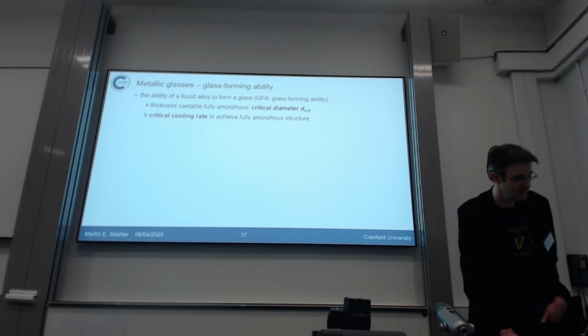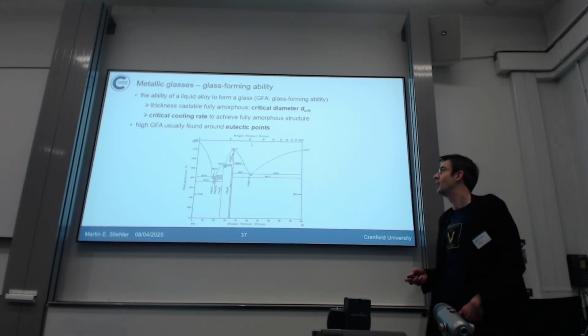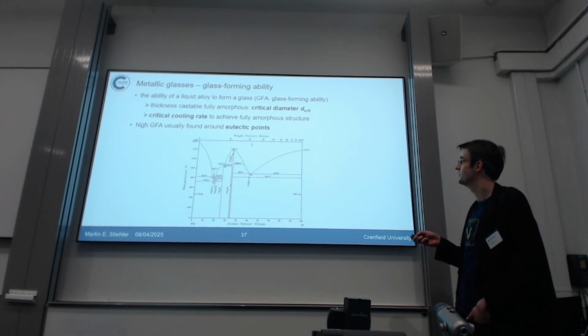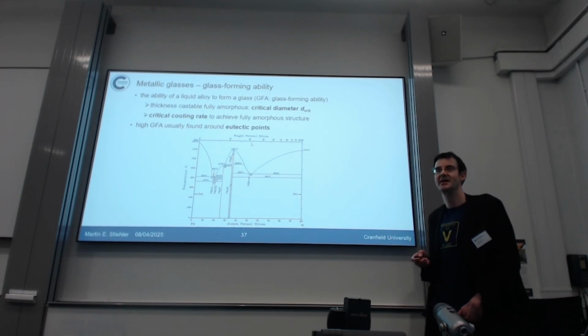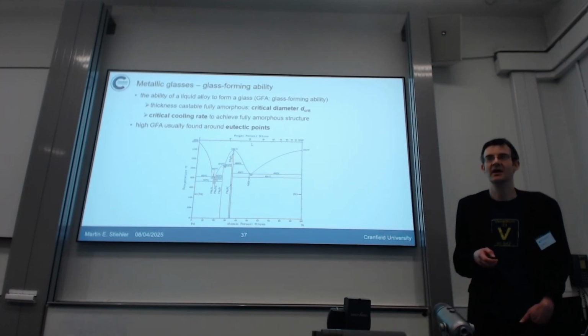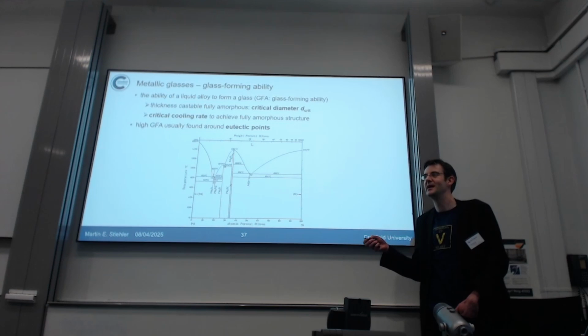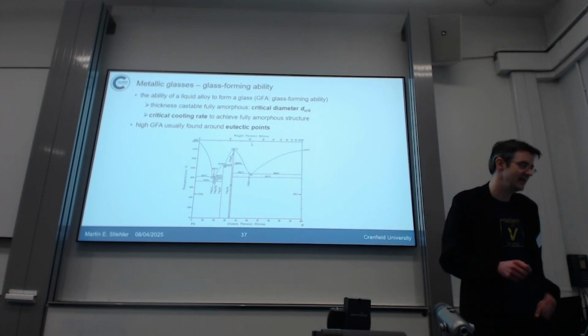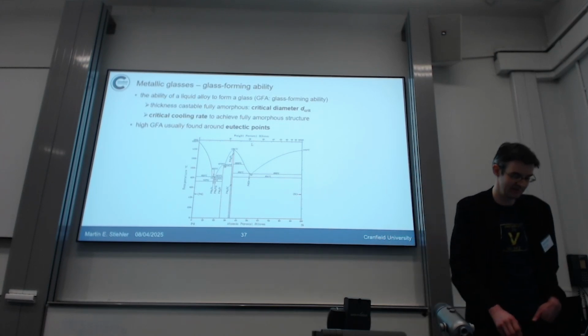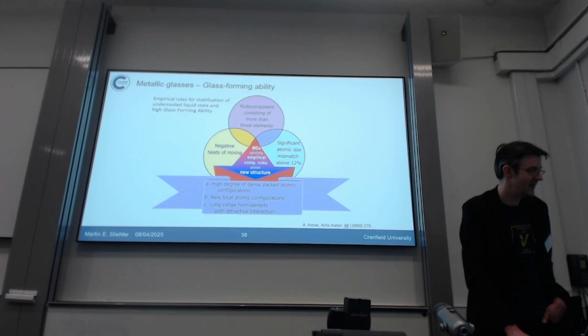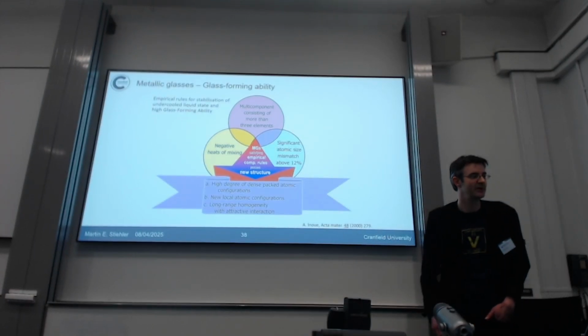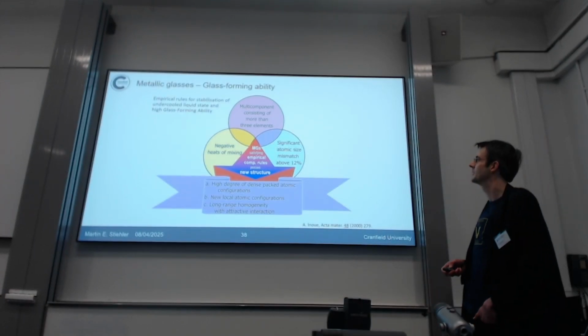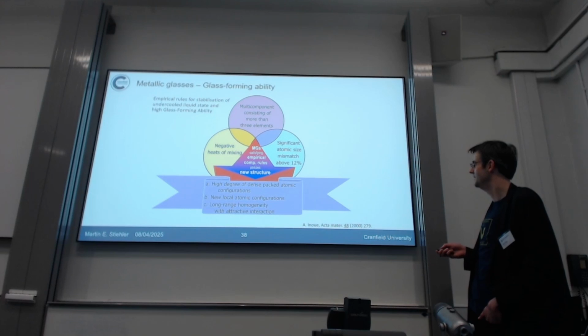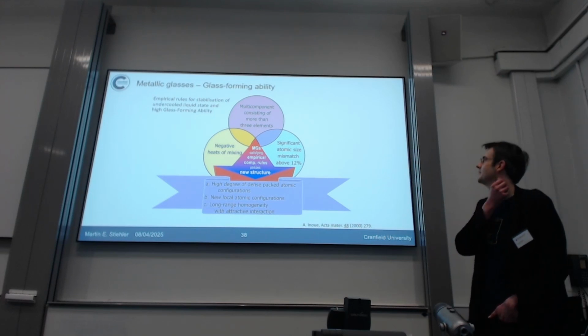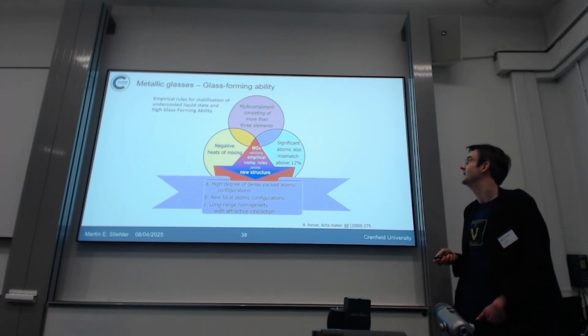The main one is to look at so-called eutectic points in phase diagrams, where you have low melting points in these materials, but you can understand that this is very hard when you look into materials which have 4, 5, 6 components. You cannot easily find eutectic compositions. Luckily, over the time, we have developed a lot of other empirical rules. Most important are the so-called Inoue rules, after Professor Akihisa Inoue in Japan.